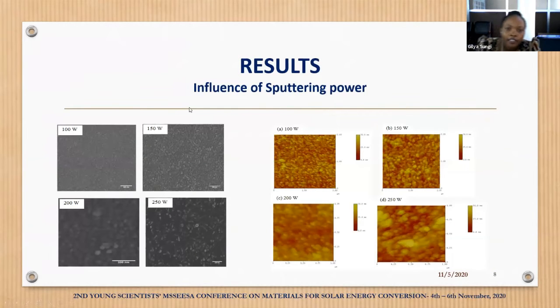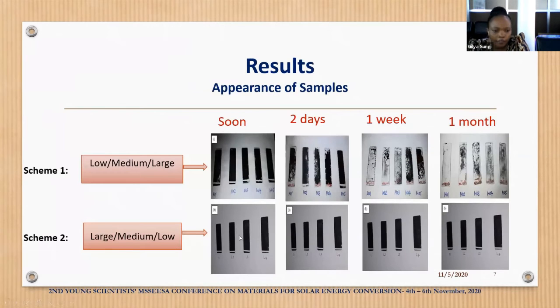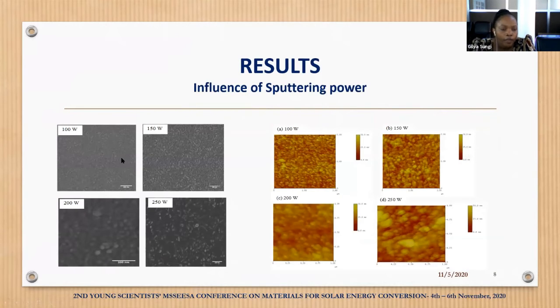And also we have investigated the influence of sputtering power after obtaining the best scheme, and you can see even from the image clearly that scheme 2 was the best choice for trilayer deposition of moly. Then the effect of sputtering power was investigated using this scheme, whereby we have found that there is uniform grain distribution using SEM and AFM images, and also an increase in grain sizes and surface roughness. And this will explain the variation in electrical and optical properties.